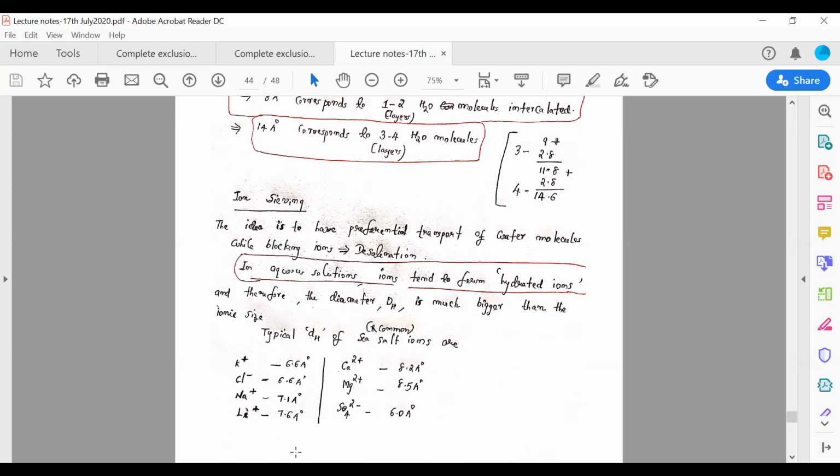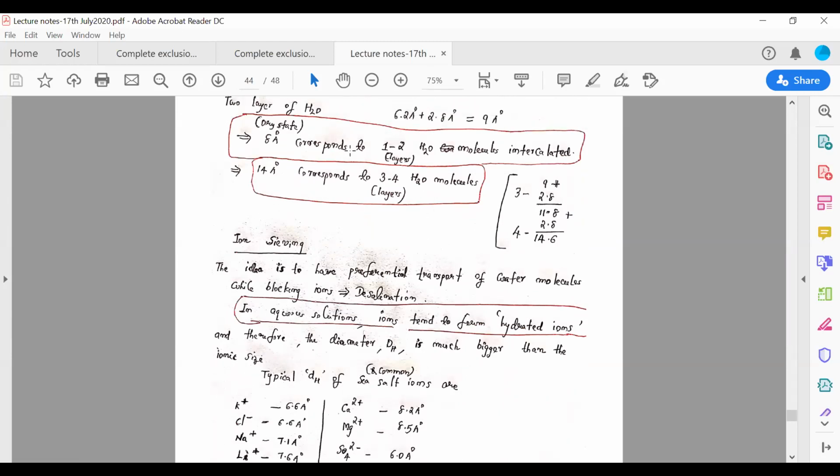This is actually a problem because with graphene oxide, from low humidity to high humidity, the interlayer expands. You have water layers in between, and that is kind of a pressure on the layers. At some point of time, this completely disintegrates because they are not mechanically very stable. There is nothing to hold them.